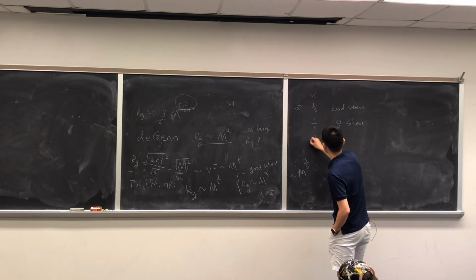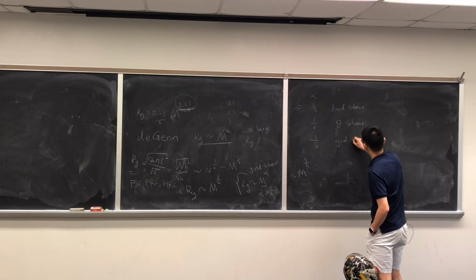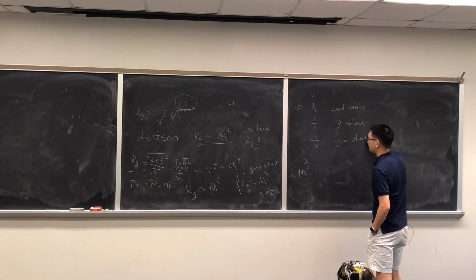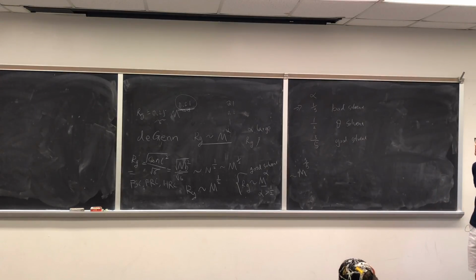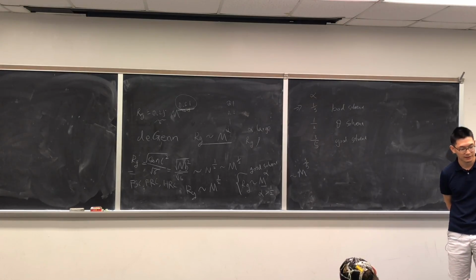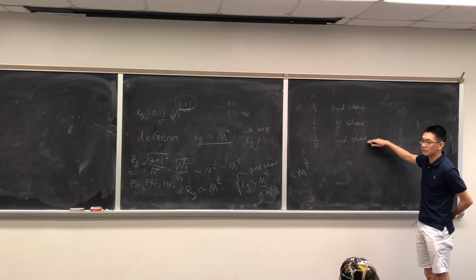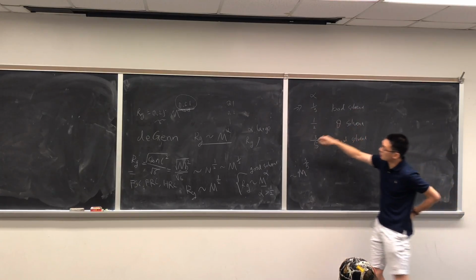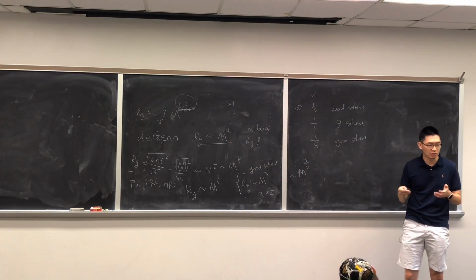If alpha is 3/5, it is a good solvent. So these three are the conditions you can rely on to eyeball and understand the general relationship between bad, theta, and good solvent. And alpha is always an exponent. It tells you how strongly Rg depends on the molecular weight. Okay?